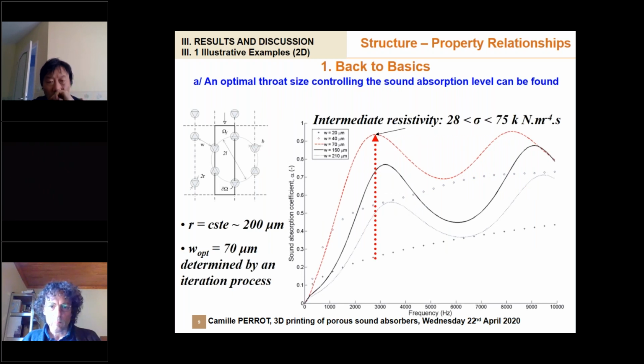What you can see when you are performing simulations is that the first significant microstructural parameter is what is called W here, or the throat size, which is the smallest interconnection size between fibers or between struts, if you are thinking in terms of a foam. As long as you reduce or expand this characteristic size, you will increase the level of sound absorption up to an optimum, and then if you open too strongly, or if you reduce too strongly this interconnection, this throat size, then you will reduce the sound absorbing behavior.